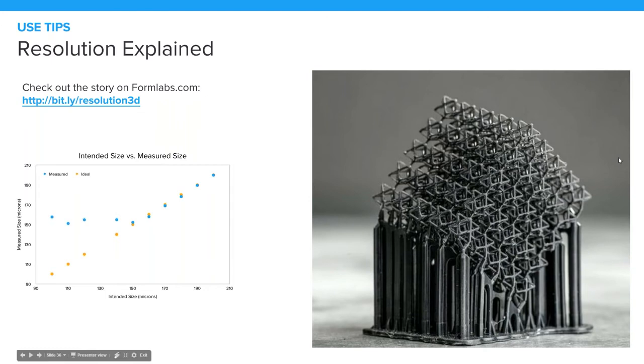The other thing here, before I jump into the z-axis, is that for comparison, with an FDM machine you're looking at 0.3 millimeters or 300 microns. So the line will have to be twice as big in order for it to show up on an FDM machine. It's one of the advantages of the SLA process. Of course, moving on to the z-axis, the SLA machines are also better there, with a little bit more resolution. For us, our minimum height is 0.025 millimeters or 25 microns. That means each of those lines could be cut a minimum of 25 microns deep before a Formlabs machine could resolve them. For comparison, an FDM machine tops out at about 0.1 millimeters, which is about 100 microns. So it's a huge leap in comparative results.